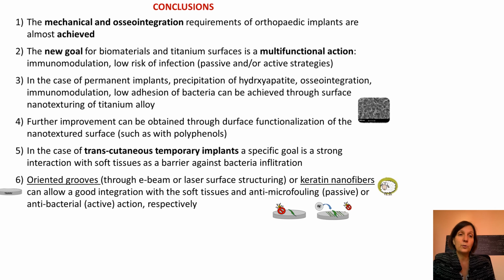Okay, so we can come to some conclusions. The mechanical and osseointegration requirements of orthopedic implants are almost achieved. The new goal for biomaterials and titanium surfaces is a multifunctional action. So we need immunomodulation, we need a low risk of infection, through either a passive or an active strategy. And we investigated a surface, useful in the case of permanent orthopedic or dental implants, able to induce the precipitation of hydroxyapatite, so it is bioactive, able to enhance osseointegration, able to induce immunomodulation with a low amount of macrophages, so with an anti-inflammatory action, with a low adhesion of bacteria.